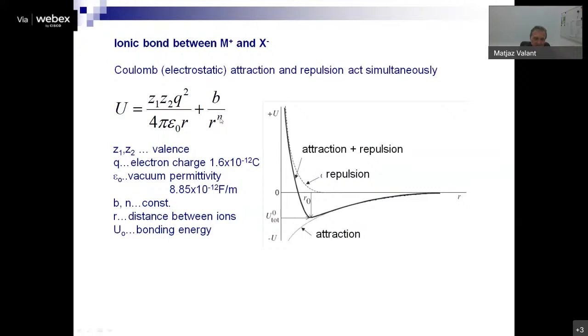And if we represent this in a plot, we would see that attraction is decreasing the energy of the system, which is beneficial for the system. We know that the lower the system energy is, the more stable the system is, while the repulsion is actually increasing the energy in the system. It is almost zero when R is high, when the distance between ions is big, but it goes very highly up when we come very close with the species. So the bottom line here is the sum of these two forces, these energy contributions. And you see this curve has a minimum here.